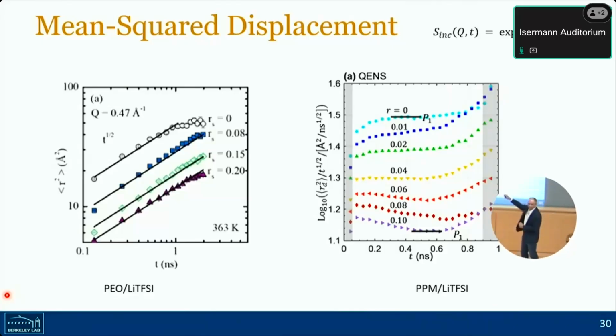All the slopes are a half. Okay? So if I had made a normalized plot, you would get the Rouse parameter plot, I would get a flat line. So this is the data from PPM, which we published last year. And you can see that the Rouse plateau, which is what I call the R equals 0, systematically goes down. And that just tells you that the friction is increasing. But there is something interesting that happens at this concentration, where you first see a decrease, a plateau, and then an increase. Okay?